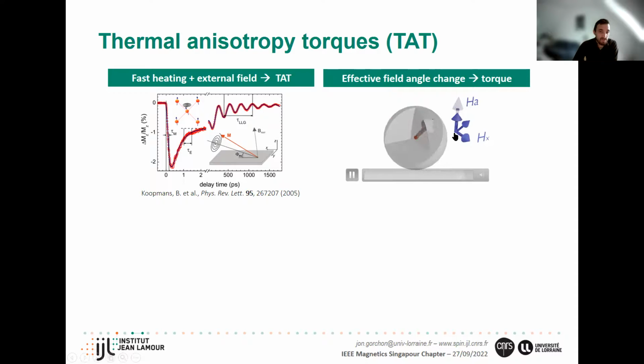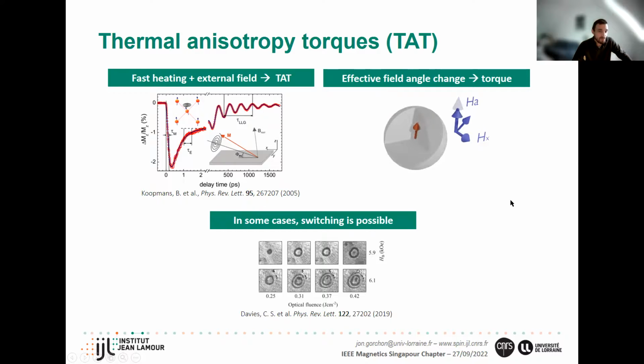And so now your effective field has a different angle, and that changing angle starts a precession. This is the precession you can see here. So this has been done for a long time. And very recently, they were able to use this precessional motion to actually cross this equator plane and switch.